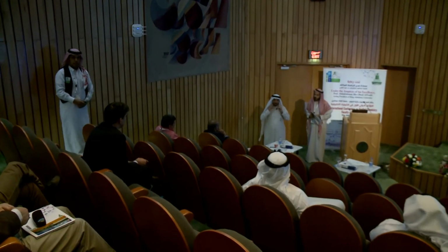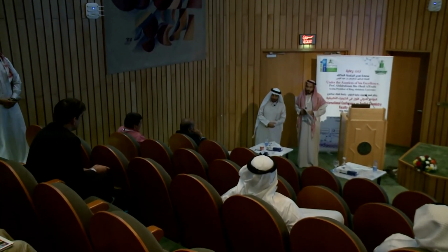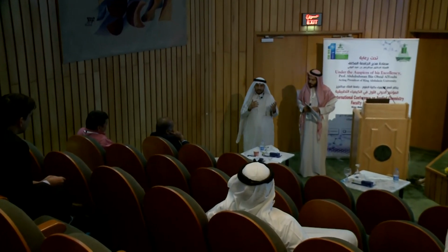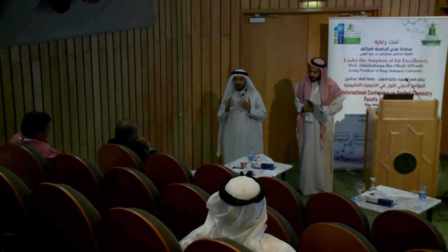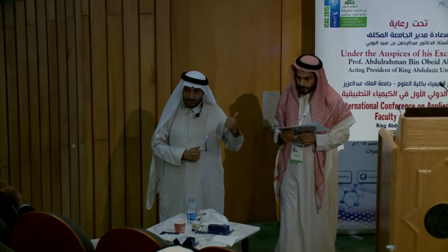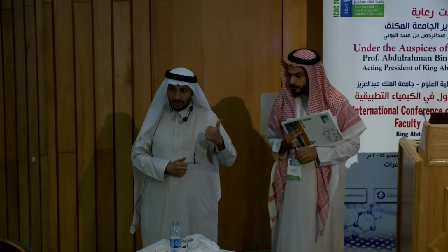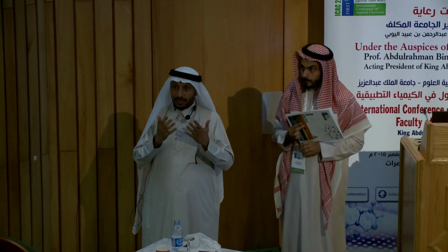Professor Stephen is asking what happens if we apply pressure to this polymeric material. Does the color change or not? If it changes, it gives you a good sensor for mechanical testing. For this photochromic material, we tried several times with the crystal itself before we doped it into the polymers. It did not give a change in the color.